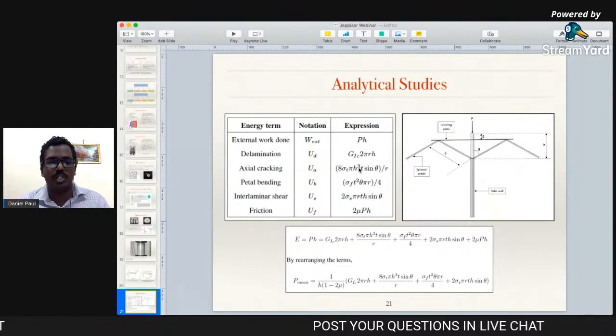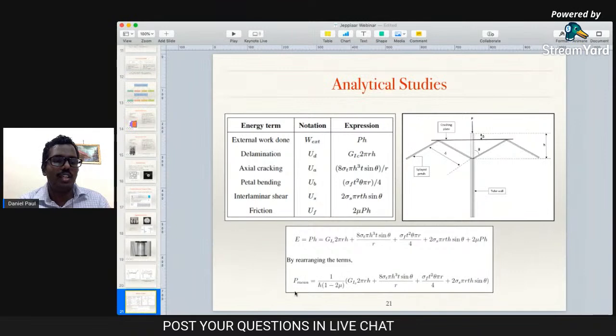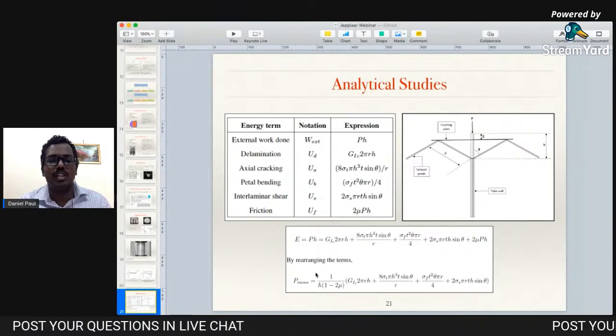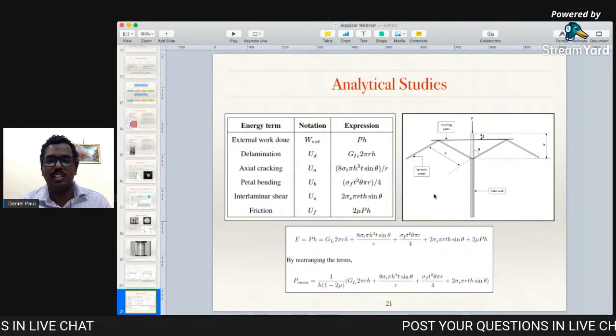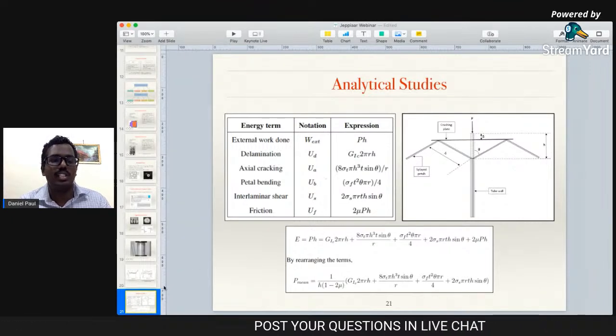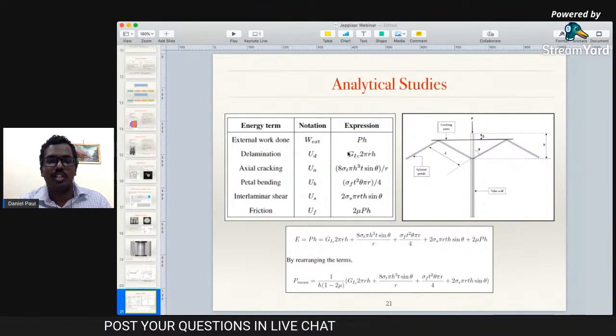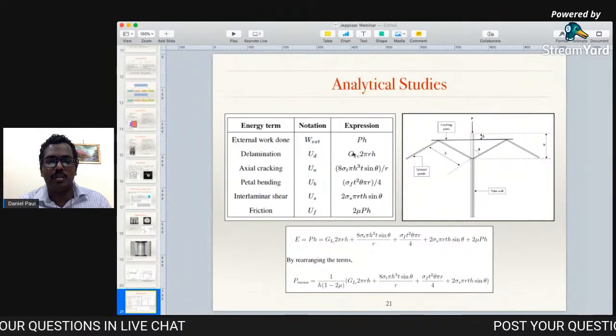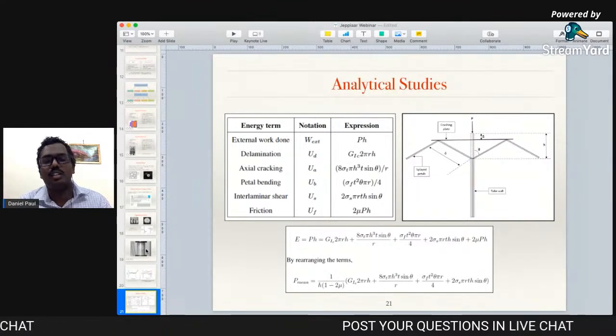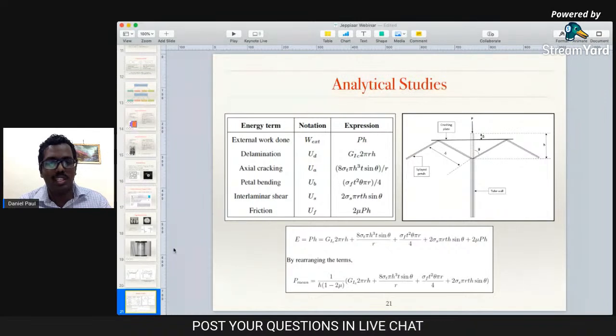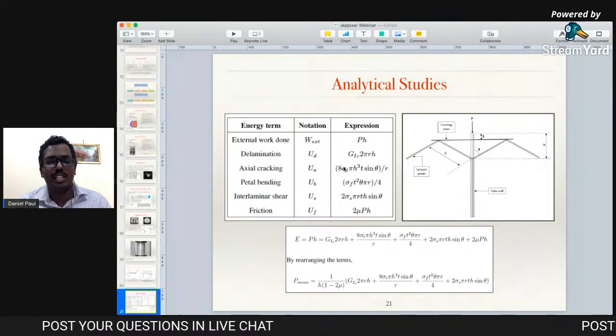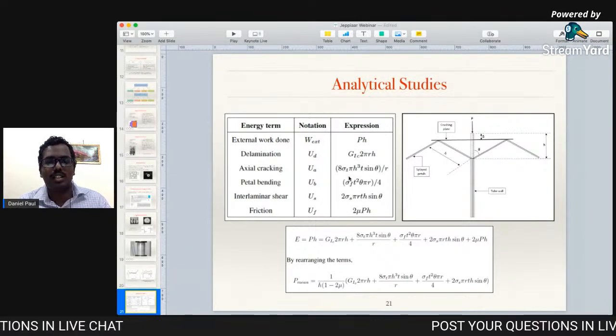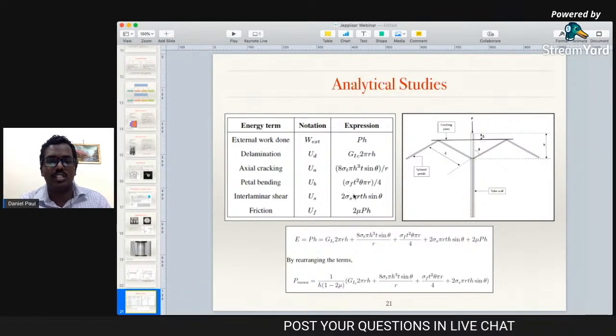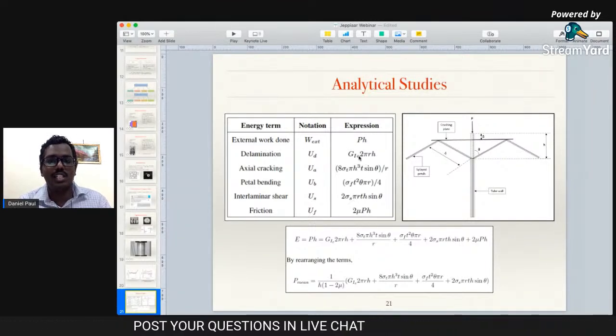By using this analytical, energy-based model, we can find out the mean crush load, and subsequently the energy absorbed by the structure analytically, without actually performing the compression test. To get these basic mechanical properties, we take a normal composite plate made of the same material and test it for normal mechanical loading such as tensile loading, flexural, shear, as well as fracture toughness.